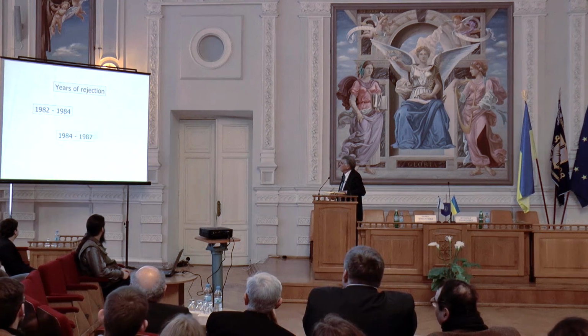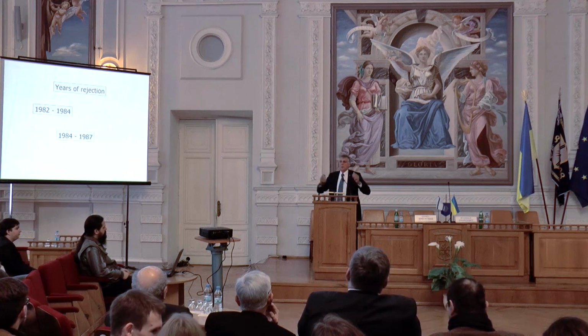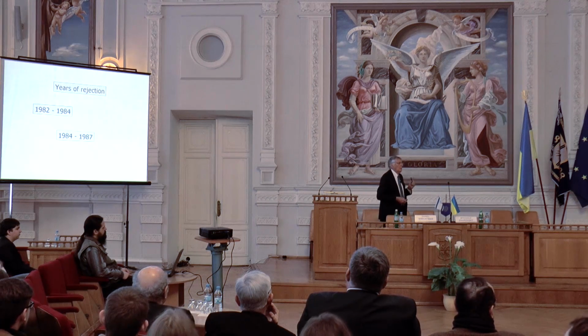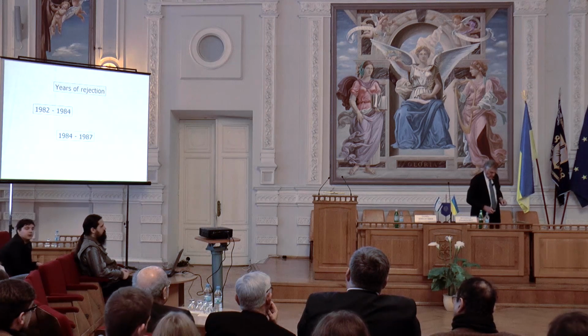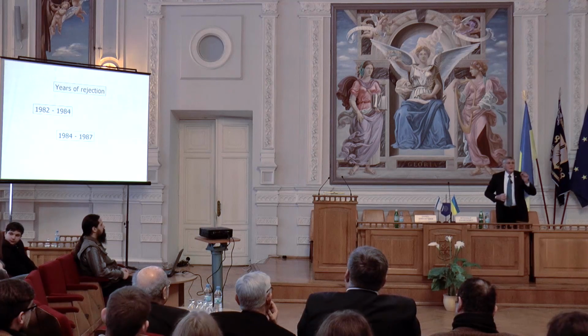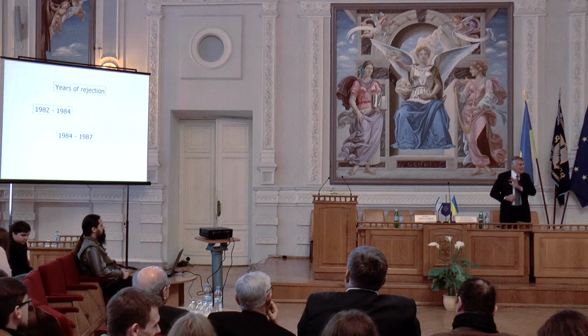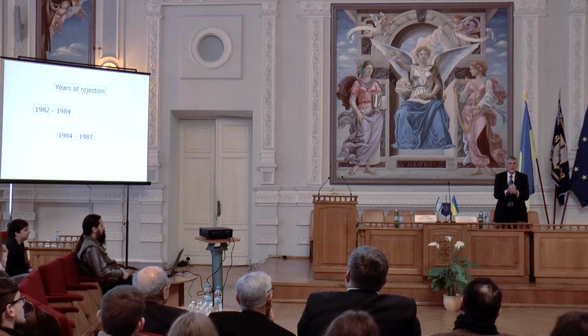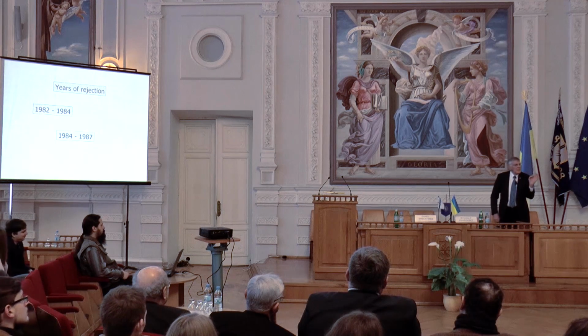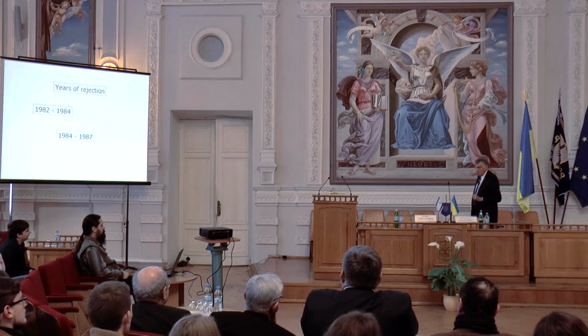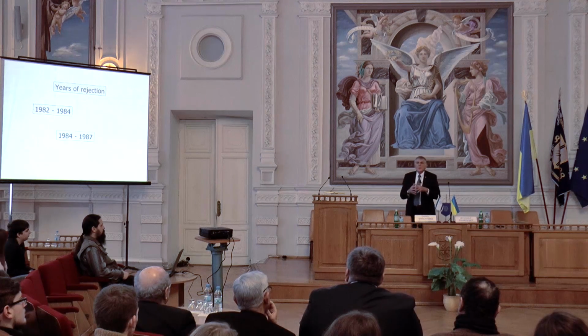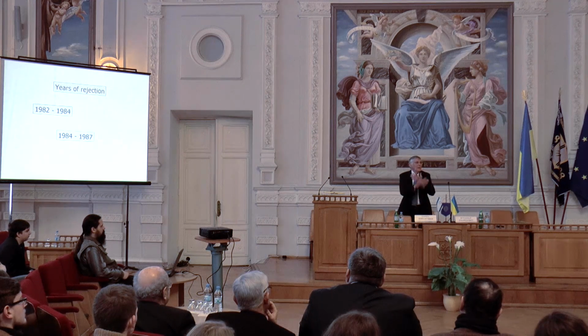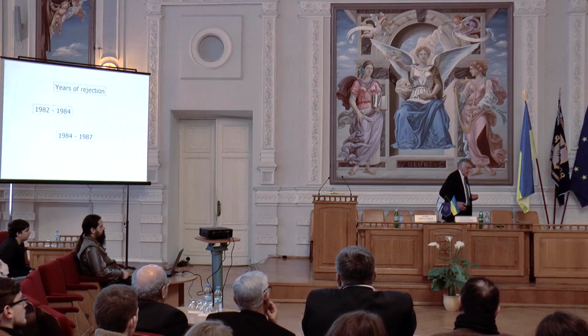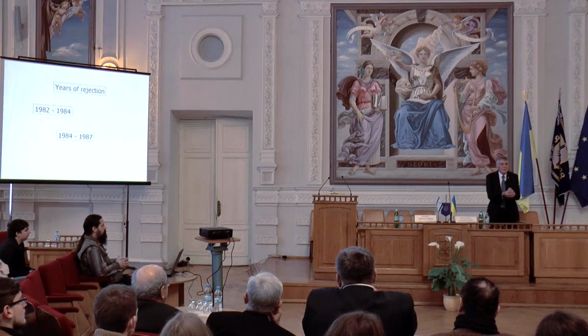Then, from 1984 to 1987, there was another major rejection, and it came from a serious body of the International Union of Crystallography. I want to remind you that when I started to talk about my project, I told you that the tool of choice was X-ray diffraction, not anything else. It was precise, it was excellent. But quasi-periodic materials were very small. The crystals were very small. And if you took a diffraction pattern from many crystals, you cannot see the rotation symmetry, because instead of points, you have rings. And you don't see the rotation symmetry, and you cannot prove that it has five-fold rotation symmetry. So they told us, hey guys, we need X-ray diffraction pattern from a single quasi-periodic crystal.